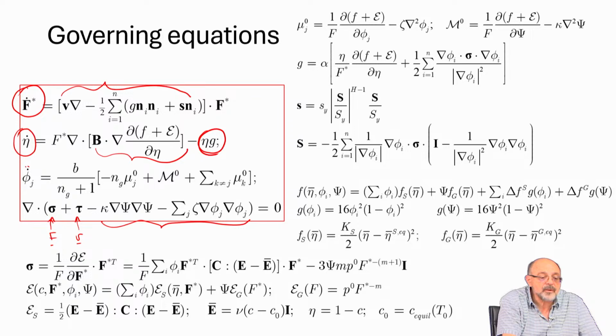My phase fields: this is the form which you obtain when you eliminate Lagrange multipliers, which impose those overall conditions that the sum of all the phases is 1. So B is the mobility parameter, mg is the number of grains, and these are potentials for each grain, which we have defined previously, and this is the potential for the gas phase.